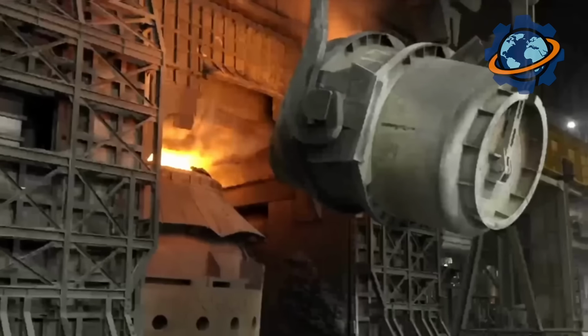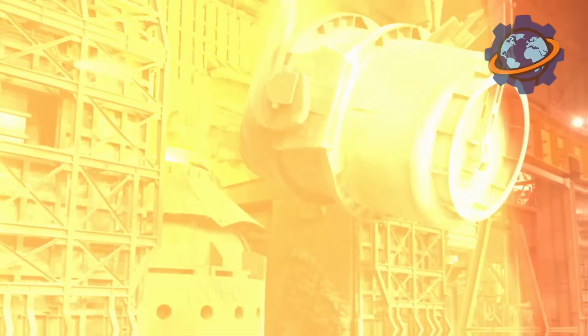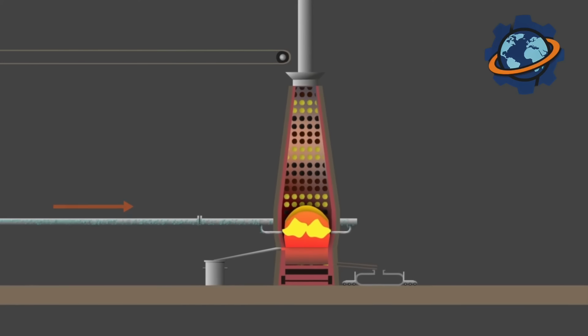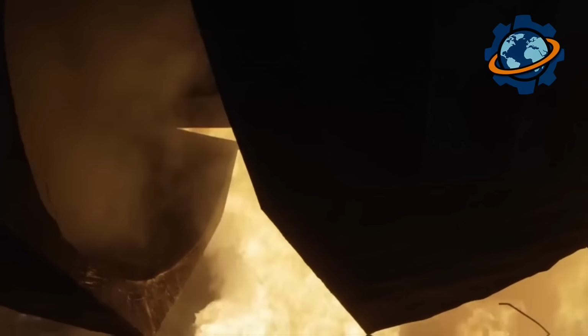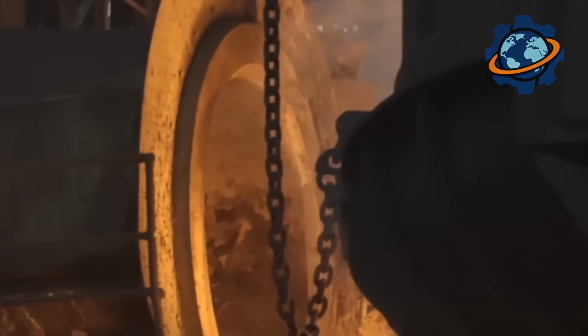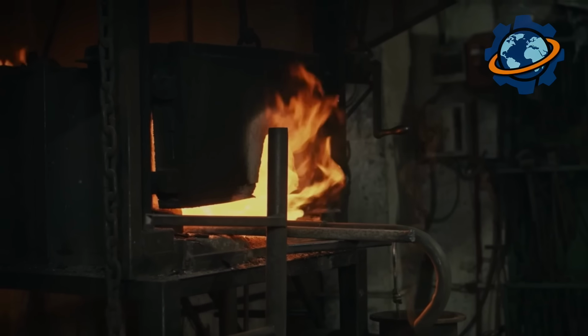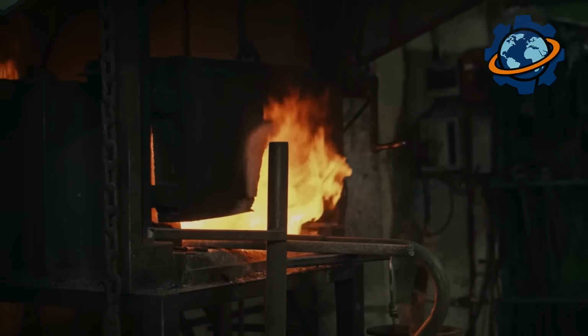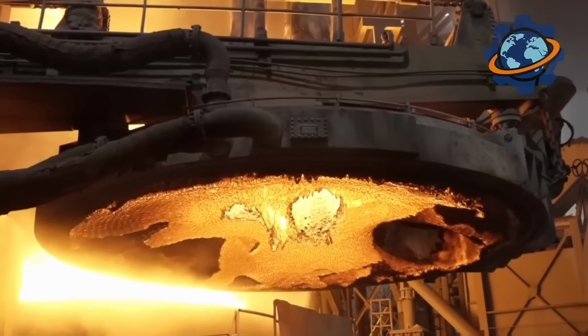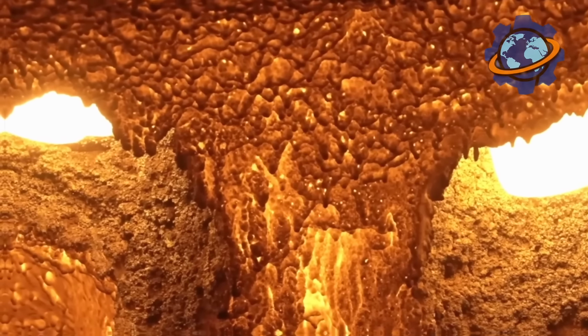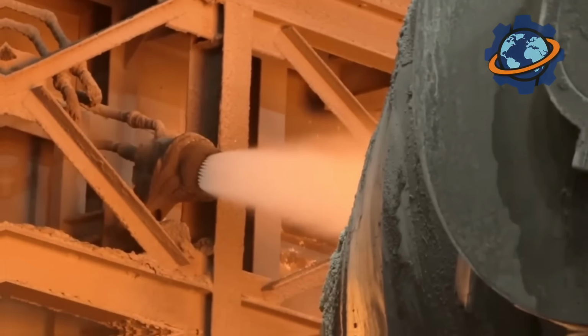Metal boils and churns. Flame tongues several feet high shoot from the converter mouth. Sparks and molten drops fly everywhere. The blowing process takes 20 minutes. In this time, 350 tons of pig iron become steel. Carbon burns down to 1% or less. The converter tilts, steel pours into a ladle.